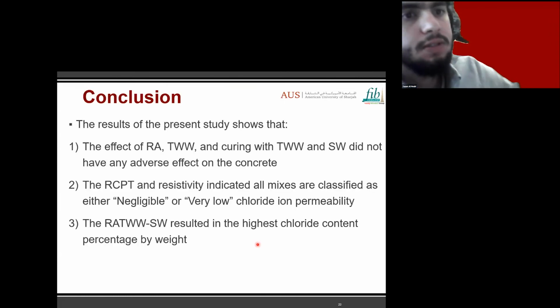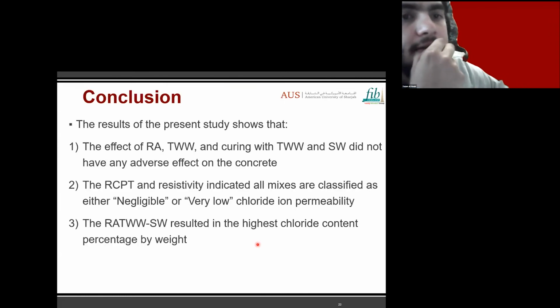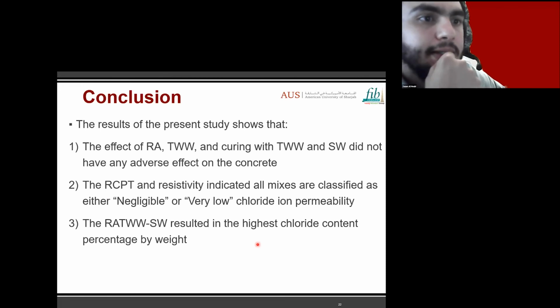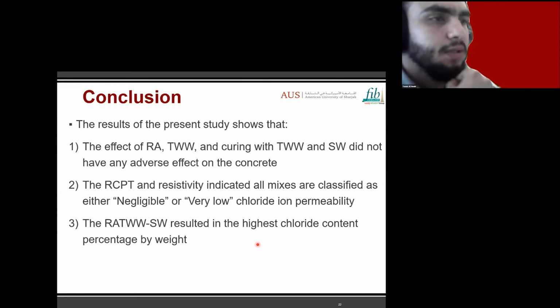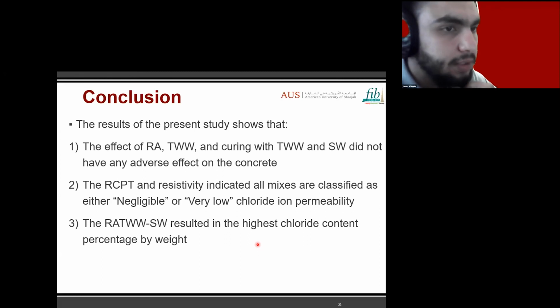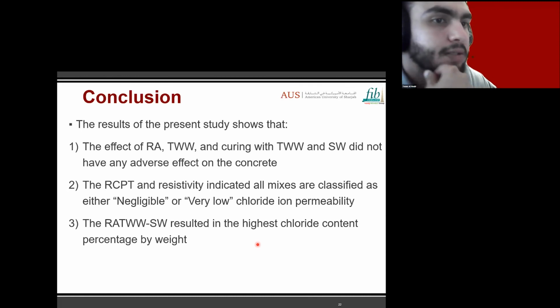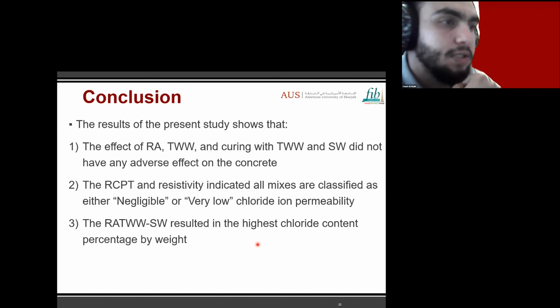In conclusion, using recycled aggregate and treated wastewater did not result in major drawbacks on the mechanical and durability properties of concrete. The RCPT test showed negligible or very low chloride ion permeability, which is a good indication of durable concrete. And finally, the highest chloride content was observed in the most severe mix, which corresponds to recycled aggregate mixed with treated wastewater and exposed to salt water.